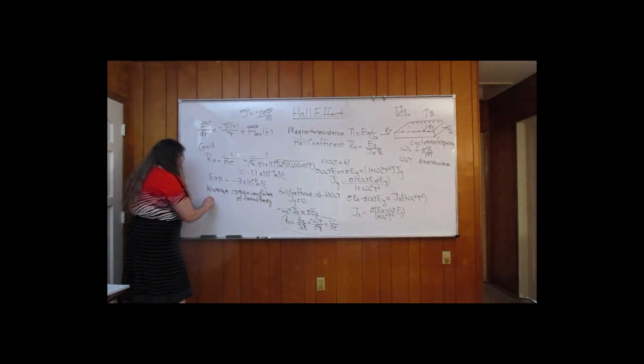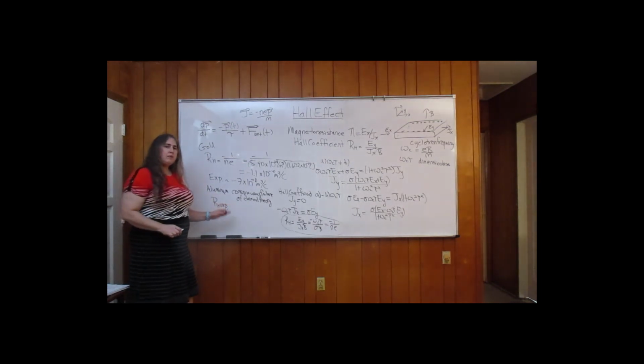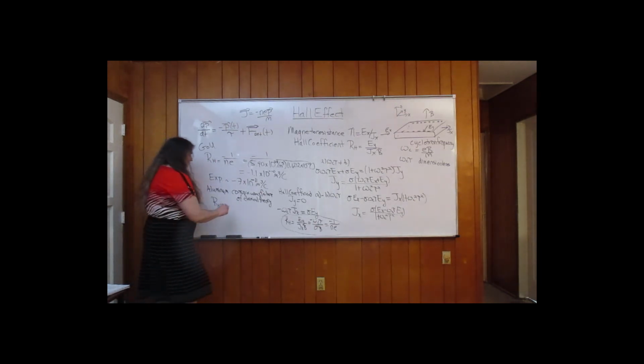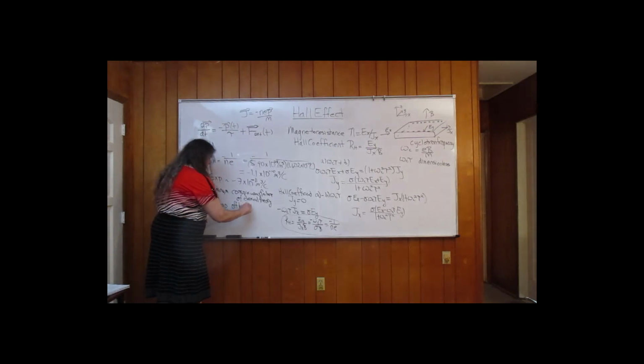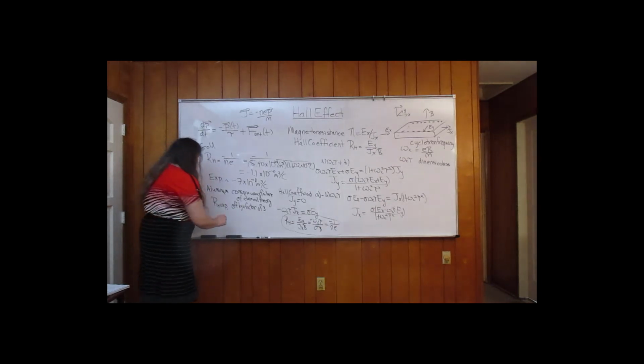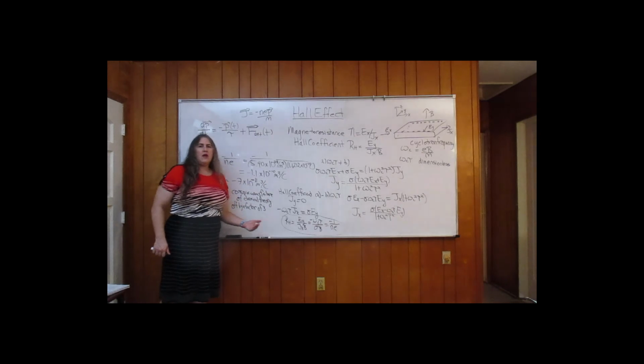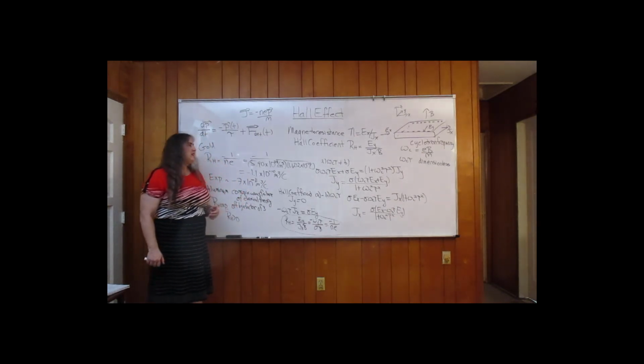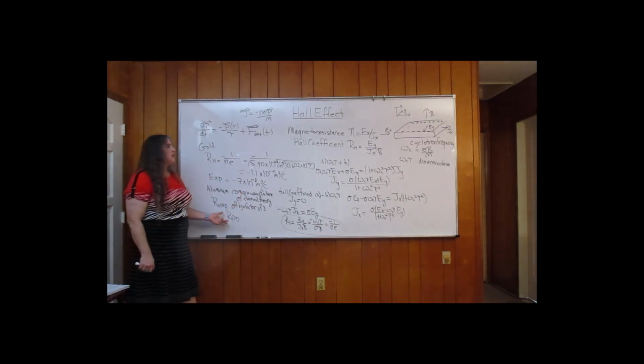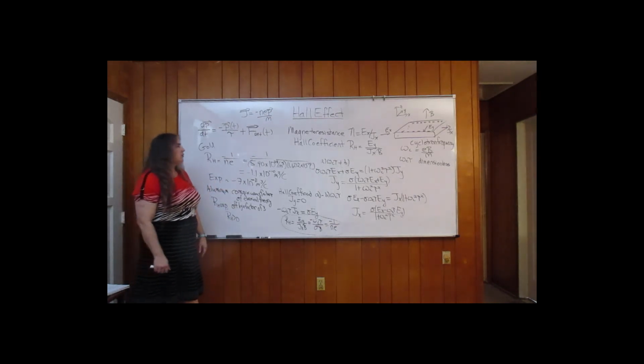And the reason for that is that the experimentally determined Hall coefficient is off by a factor of 3. Worse for classical theory, the experimentally determined Hall coefficient in fact is positive. Now, if this is positive, that would tend to indicate that the charge carriers are positive, not negative. So the answer to that lies in quantum mechanics, can't be answered with classical theory.